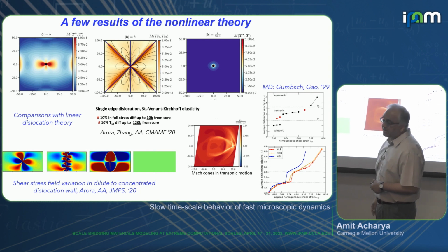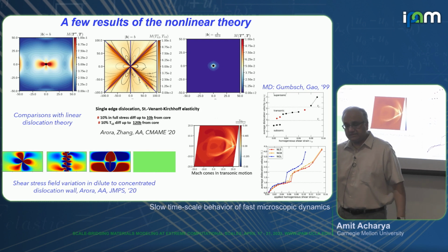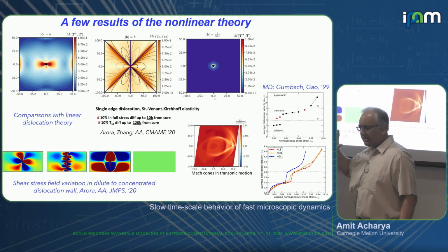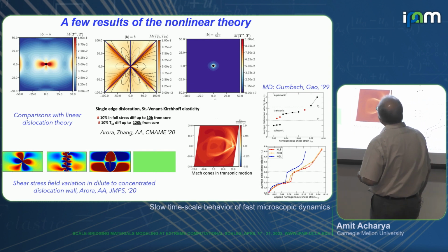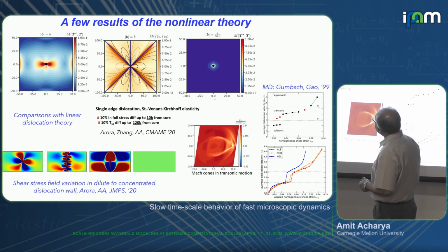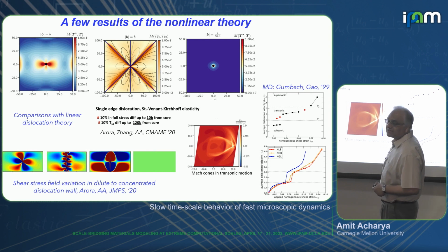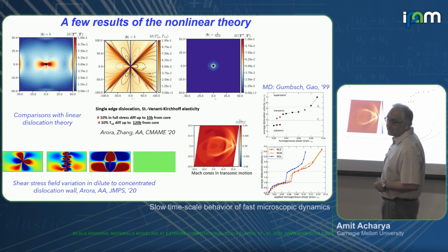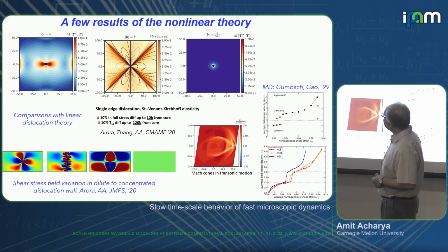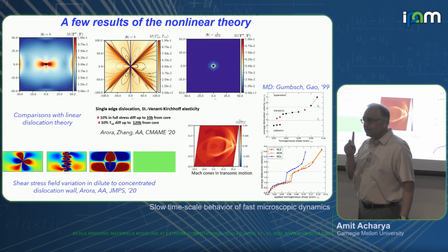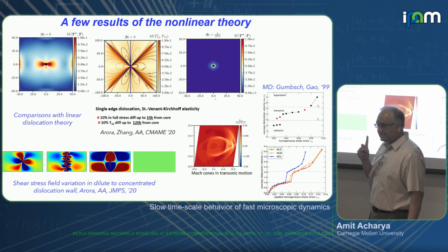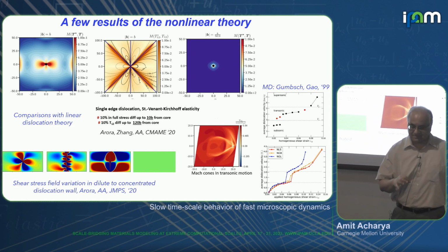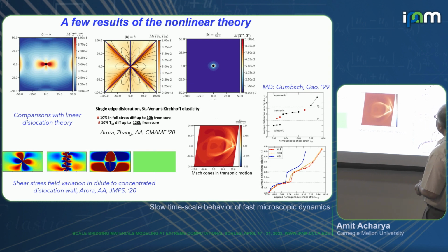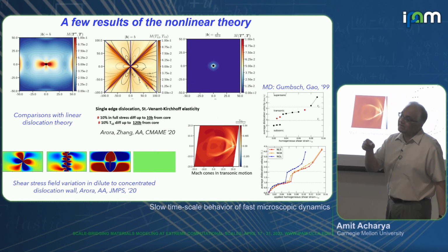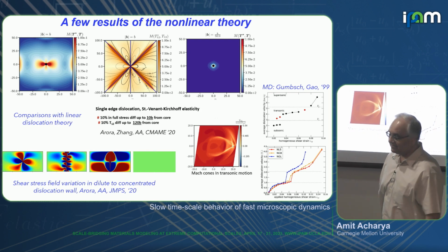Here, up to 10 Burgers vector from the core, there are 10% differences in the energy for a Saint Venant-Kirchhoff material. Okay? And if you look at the edge dislocation and the shear stress field, sure, the comparison between linear theory and nonlinear theory along the x-axis, which is what everyone will show you, that's actually zero, no error. But along these diagonals, up to 120 Burgers vector from the core, there are 10% differences. And if your dislocations depend upon stress, this is something to think about. And then you ask, okay, what is the strength of the Burgers vector at which the linear theory and the nonlinear theory match?